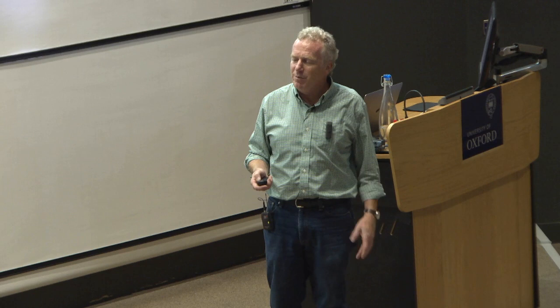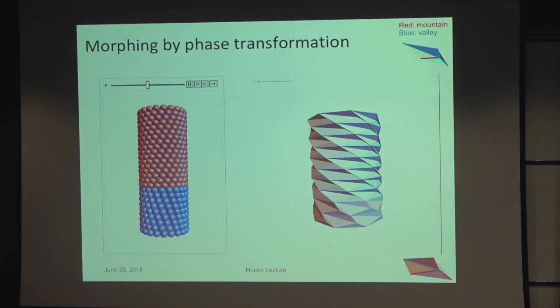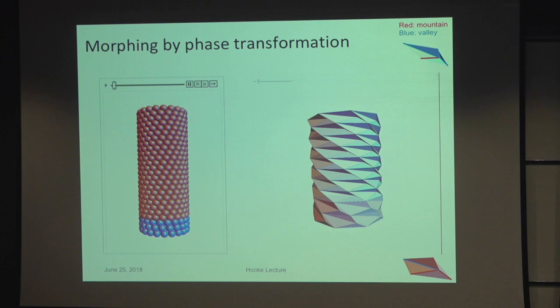In fact, the idea of compatibility we're using for origami, but it's for two helical structures. Okay, so that provides a nice way of morphing in a phase morphing origami structures. We can arrange a compatible interface, and then by moving that interface we can do morphing of the structure. I'll show you again. So this is twisting and also increasing its length.